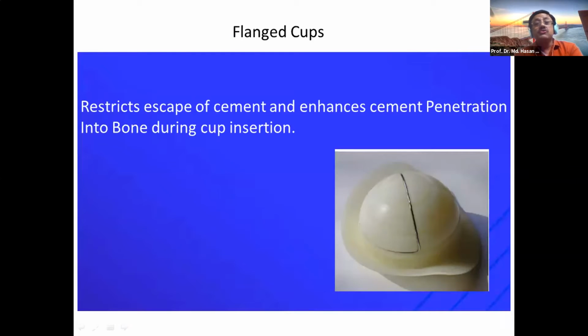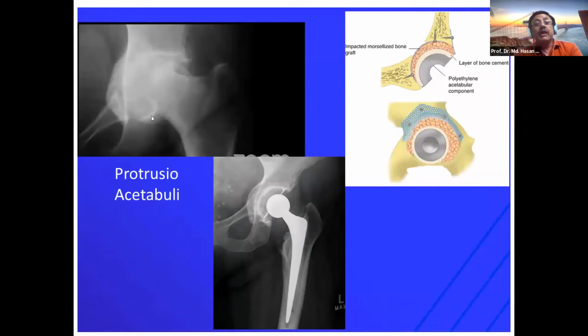Sometimes you use the flanged cup when it restricts the escape of cement and enhances cement penetration into bone during cup insertion. And see one problem. Here there is a protrusio acetabuli, and the center of rotation of the hip is medially displaced. So you have to restore the center of rotation. How? You have to put the morcellized bone graft with impaction grafting, and then you can use the bone cement. And this is a cemented prosthesis with bone grafting. So you restore the center of the hip.